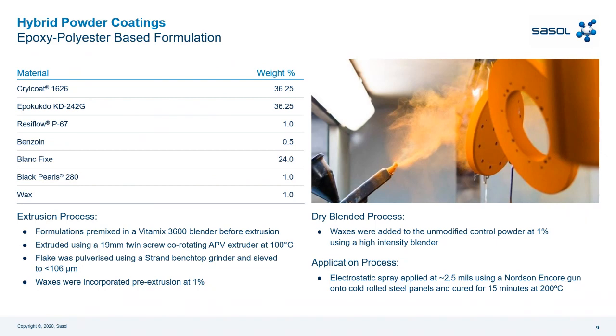So you can see that there is Crylcoat 1626 from Allnex, a carboxylated polyester resin, 36.25%. Then Epokukdo KD242G that comes from Kukdo Chemical, a standard solid epoxy resin, 36.25%. ResiFlow P67, 1%, is a flow or leveling agent. Benzoin, 0.5%, is the degassing agent. Blanc Fixe, 24%, is barium sulfate that comes from Venator and is a helper of the pigment. Then Black Pearls 280 from Cabot Corporation, 1%, is the normal carbon black. And the wax, as I mentioned before, 1%.